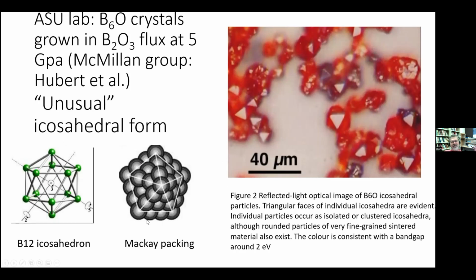But if you're doing EELS, in addition to simply X-ray diffraction and the normal, then you can really tell what's going on in your samples. One of the neatest things he made were these icosahedral particles, which here they are in microscope view. This is B6O, and it's a semiconductor, so it's got this red color. It's a wide bandgap semiconductor, but it has some color, and it's based on a boron icosahedron, and he wasn't trying to do this, but when we tried to grow single crystals in B2O3 flux, so B2O3 melts, and then excess boron forms B6O, boron suboxide.